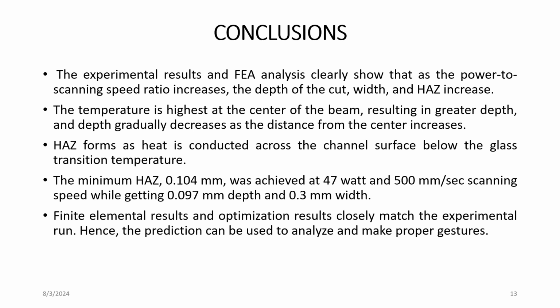The minimum heat affected zone, 104 micrometer, was achieved at 47 watt and 500 millimeter per second scanning speed, while getting 0.097 millimeter depth and 0.3 millimeter width. Finite element result and optimization result closely match the experimental run. Hence, the prediction can be used to analyze and make proper decisions.